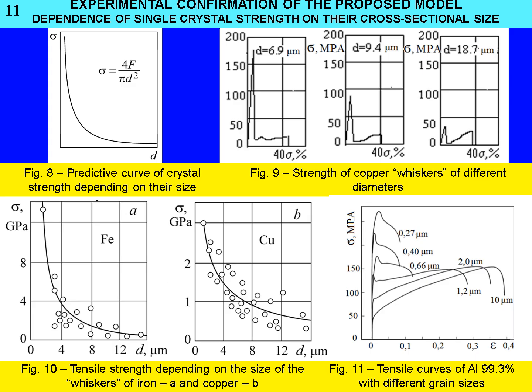The yield stress of thin, whisker-like crystals is extremely high. However, as the diameter increases, the yield stress decreases because the surface effect diminishes. For diameters above 50 microns, it approaches the yield stress of conventional metals. In polycrystalline metals, the yield stress also decreases with increasing grain size (Figure 11, Hall-Petch relationship).